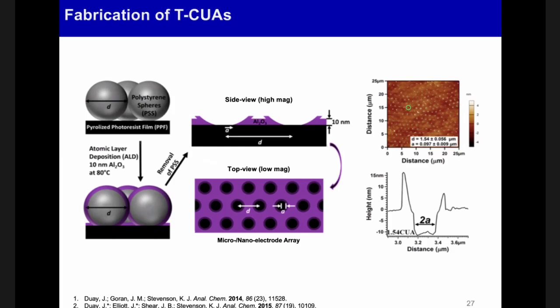So what you're left with is basically these areas of pyrolyzed photoresist film, which is our electrode. And then the rest of it is the aluminum oxide layer. And here you can see this top view where D is the diameter of the polystyrene sphere, and A is the radius of each individual electrode. There's a mathematical model where we can predict the sizes, and we also took AFM images to confirm what the sizes are. So this is just the top view where you can see the little individual electrodes in this array. They're all connected in a parallel circuit.